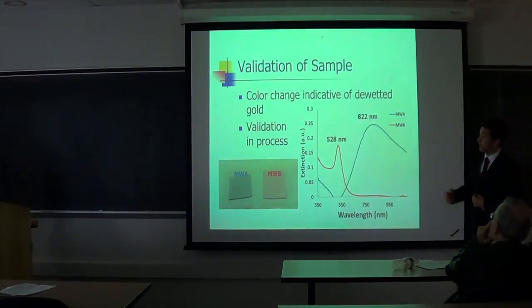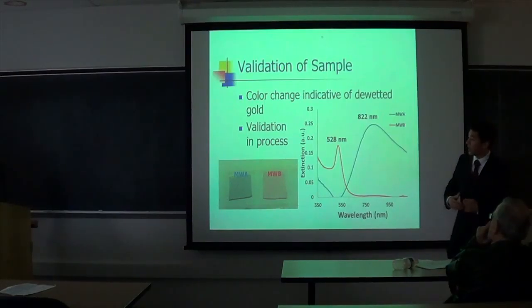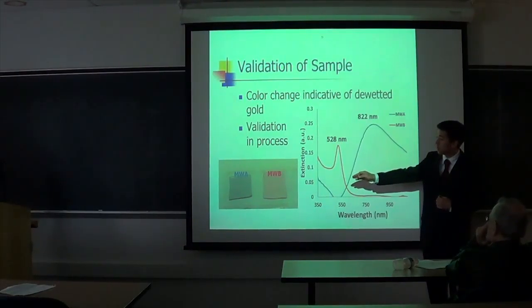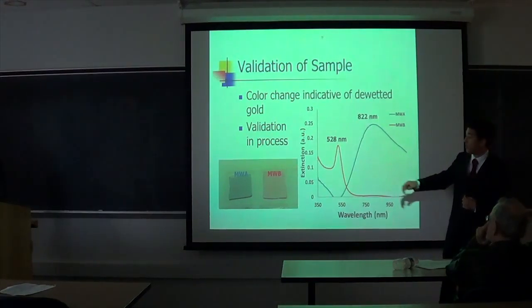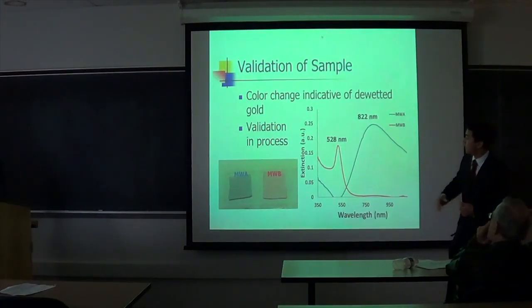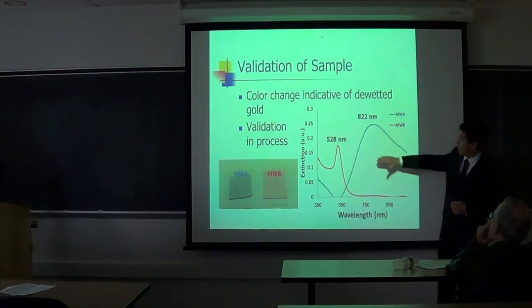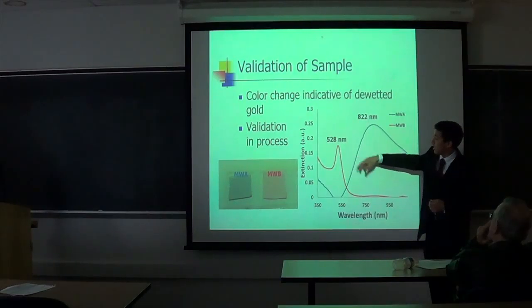This is the validation of our sample that we were able to create. So MWA is a non-de-wetted thin film of gold on a substrate, while MWB is a de-wetted thin film of gold. In this validation process of spectroscopy, we got a peak at 528 nanometers.